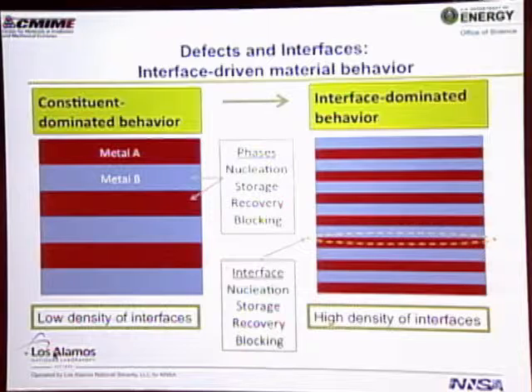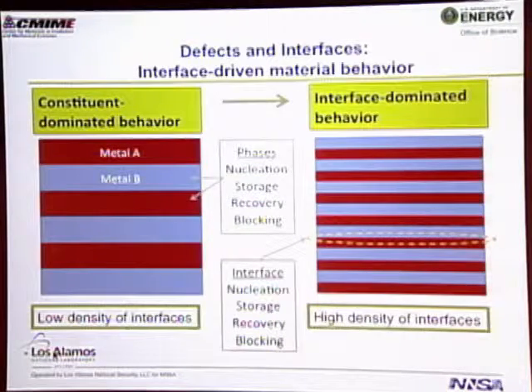So when we think about a layered composite, typically what we have is constituent-dominated behavior, where the phases of the material that you start with, metal A and metal B, dominate the nucleation, storage, recovery, and blocking of defects such as dislocations. That's what dictates the properties that you get out. Now, if we start adding more and more interfaces, what we find is that the interface dominates these processes. And as such, it doesn't matter so much anymore that you make a material out of copper and niobium, silver and copper, zirconium and niobium. What starts mattering is what the interfaces are between them and what their structures are. You can imagine that this gives us boundless potential for changing the properties of materials and controlling those material properties just by forming the correct kinds of interfaces, just like Feynman said.